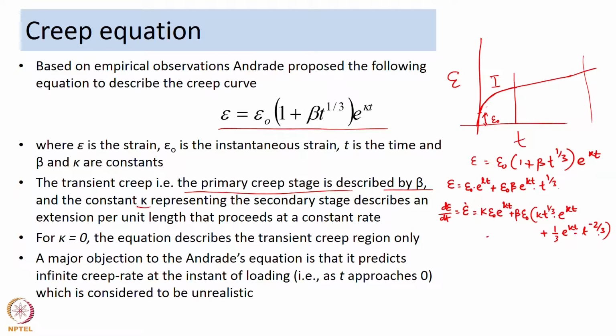So, if you look at this equation, if t tends to 0, then since epsilon dot has a term that includes t to the power minus 2 by 3, epsilon dot will automatically tend to infinity, and that was the primary objection raised to Andrade's equation, because it is unable to explain this, as epsilon dot tending to infinity is not true.